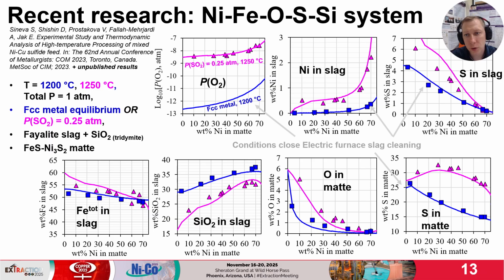In the available literature, there were some gaps. They were measured recently by my co-author Dr. Svetlana Sineva. Namely, for conditions with high PSO2, shown using magenta color, the solubility of sulfur in matte was not previously measured. And now we can compare it with model predictions. Also, the conditions close to equilibrium with the metal, shown with the blue color, were not studied enough. Conditions in equilibrium with metal are close to what we can achieve in electric furnace if mattes are over-oxidized during smelting, but then reduced back. There is a potential for lower nickel in slag.